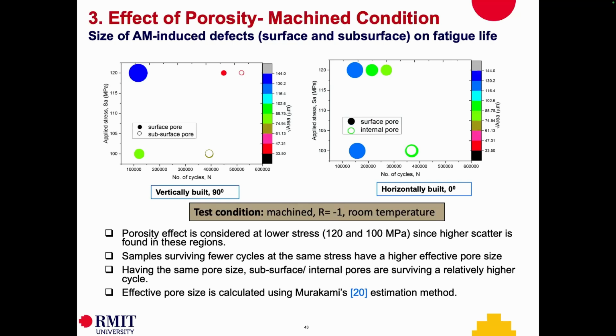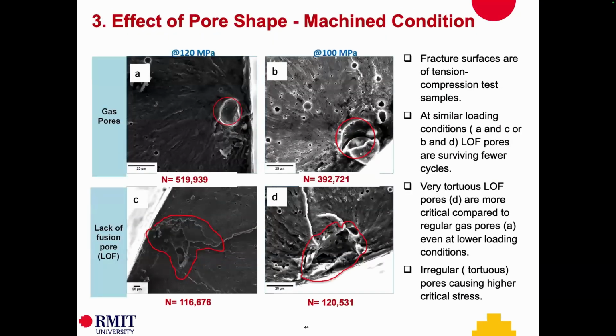However, look at that solid and hollow pores. If the pore is close to the surface, same pore size, a subsurface internal pore is less critical than a surface pore. If the pore of same size is on the surface, it will give you lower fatigue life. If the pore is internal, although the stress level is the same, you get a much higher fatigue life, and that happens in both horizontally built and vertically built cases. So this is a good take-home message for us. Whether the pore is on the surface or internal matters, and if it is internal, then the size will dominate. If it is on the surface, then the surface effect will dominate.